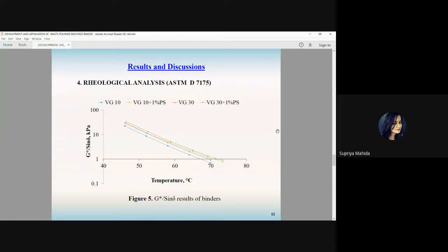The fourth test we performed is the rheological analysis, for which we proceeded with ASTM D7175. Figure 5 shows G star by sin delta. G star by sin delta is the rutting parameter which we get from the dynamic shear rheometer. That is the instrument with which we shear a small sample of the binder, and it gives results as shown in figure 5. For every temperature, we have the G star by sin delta value. The higher the G star by sin delta value, the higher the rutting resistance.